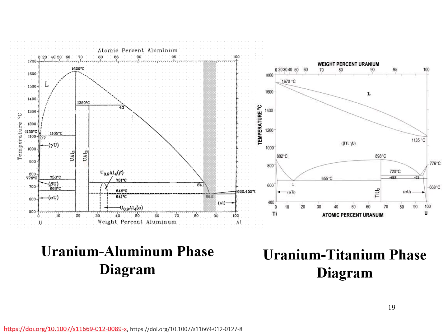If we mixed uranium by weight with 25% aluminum, it would fall right about here, and we would have a mixture of compounds based upon where it falls on this phase diagram. Over here, the 25 would be primarily the uranium-3 aluminum with a little bit of the uranium-2 aluminum.